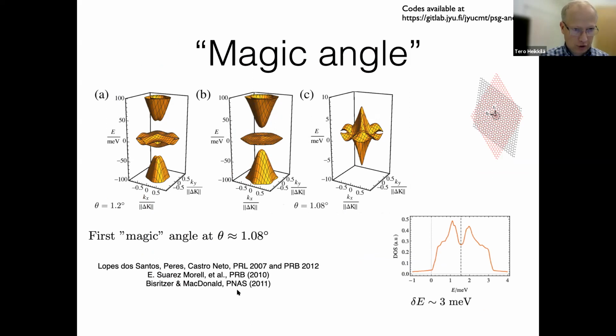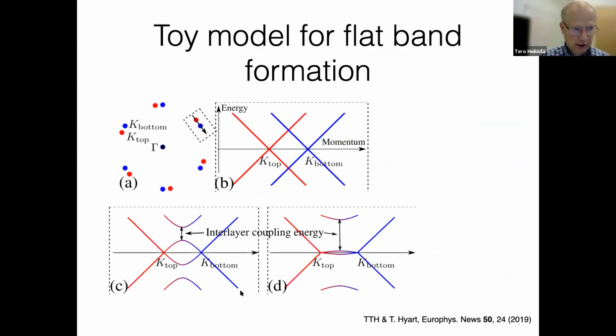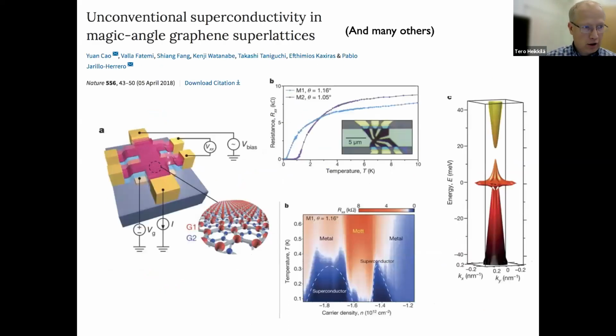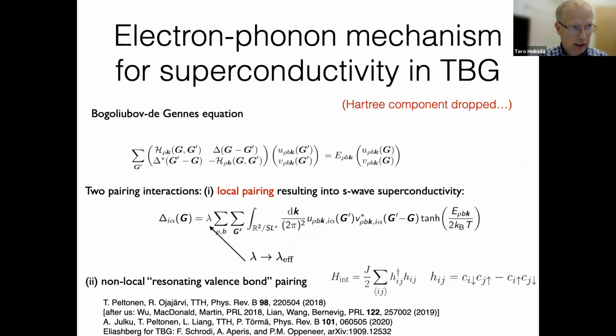Then the superconductivity is more recent. Let me go to those superconductivity observations. This is what Pablo Jarillo-Herrero showed 3 years ago, and now also many others, but this was the first experiment. They find, as a function of the charge density, these superconducting states, which in this experiment have a TC of 0.4 Kelvin, but people have gone up to 2 or 3 Kelvin in TC.